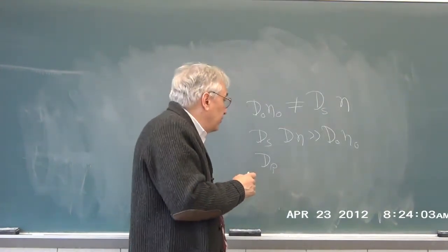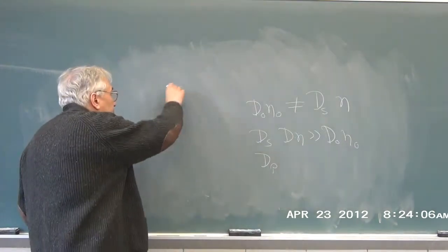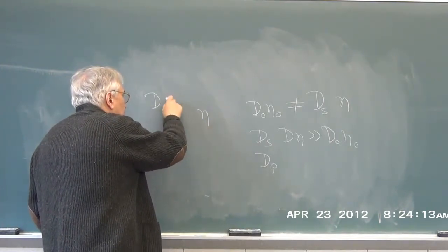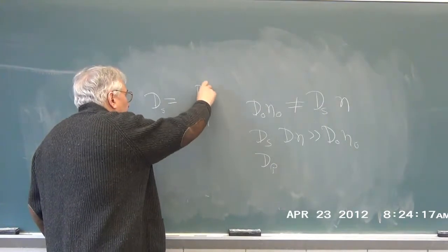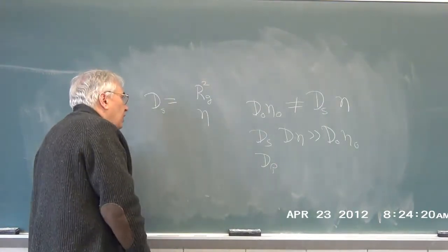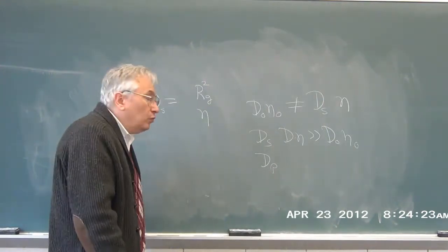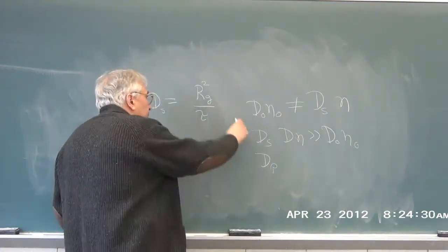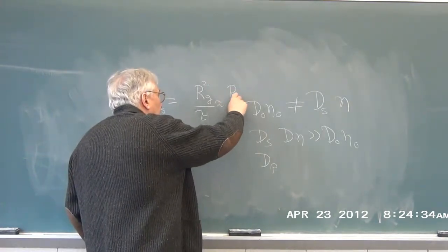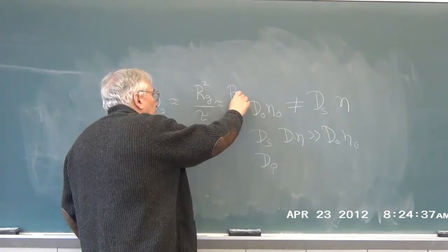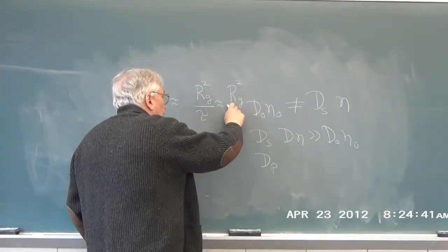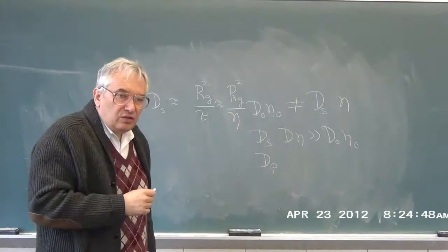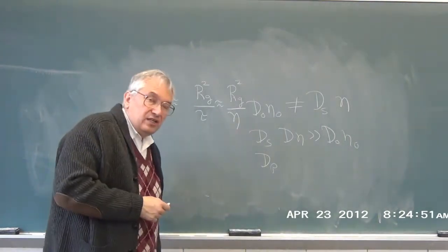And the reason it's interesting is that there are a number of theoretical models that propose that we can relate the diffusion coefficient and the viscosity of the solution, namely the diffusion coefficient is, say, the time required for the polymer to move a distance, I'm going to insert an intervening step, divided by some critical time. And this is a proportionality. This is Rg squared, the size of the polymer chain, which is of course not quite concentration independent, divided by the solution viscosity. That is, the proposal is that d and eta are related as indicated.